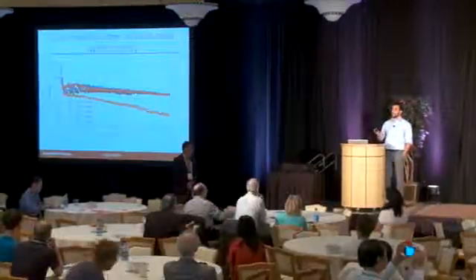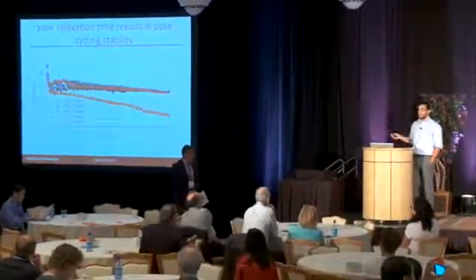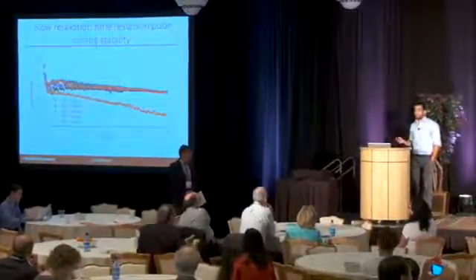So, I didn't mention, these first 3 cycles are at C/20 rate, which is 1 charge cycle per 20 hours and then a discharge cycle per 20 hours. So a 40-hour full cycle. And then we switch to C/10. And that's a standard cycling procedure that's been put out by a couple of the DOE programs on battery stuff. So some of the capacity loss just comes from charging it more quickly, so kinetic effects.